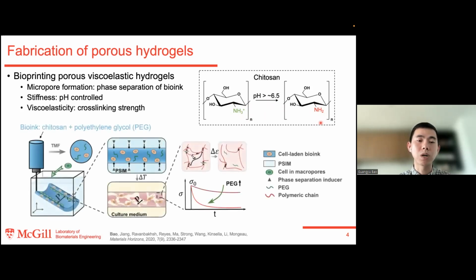So we use this property to bioprint viscoelastic hydrogels with micrometer-sized pores for the first time. The bioink we use contains chitosan and polyethylene glycol, and we use the embedded printing technique to complete the bioprinting. If we take a close-up view, after the printing, we can release the salt pre-embedded inside the supporting matrix, and it can diffuse into the weakly acidic bioink solution to increase the pH. Upon the neutralization of the pH, the chitosan will phase separate to form a polymer-rich and polymer-poor phase.